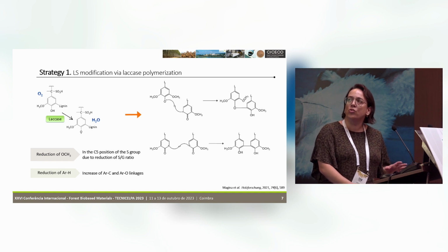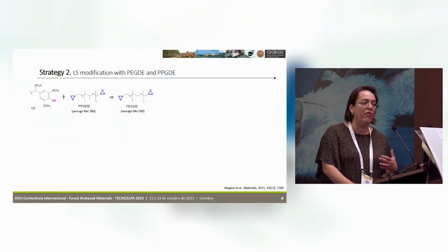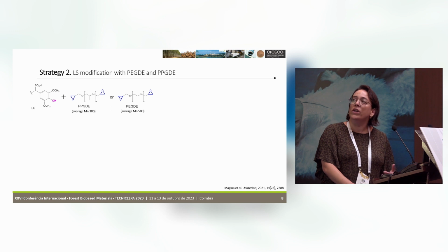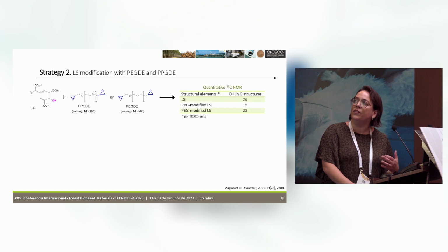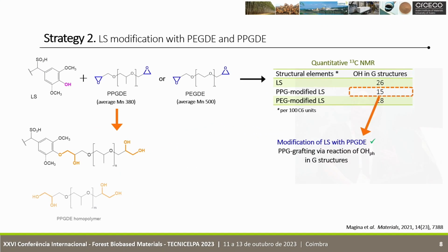The second approach to enhance the dispersant properties was the modification of lignosulfonates with epoxidized derivatives of polyethylene glycol and polypropylene glycol. In the case lignosulfonates were modified with polypropylene glycol, there was a significant decrease.